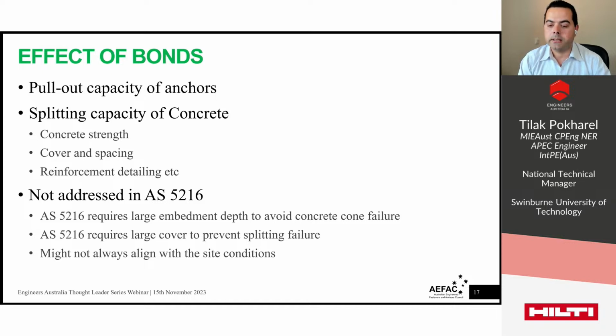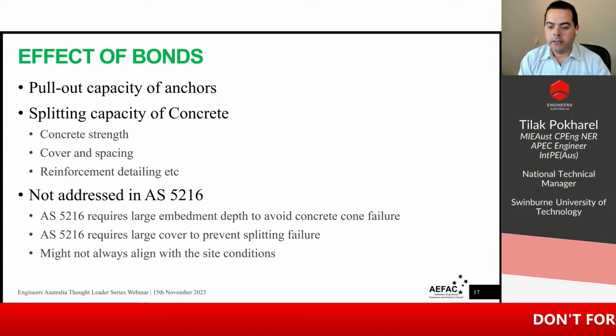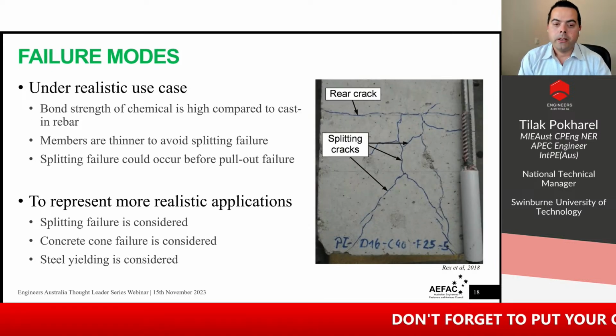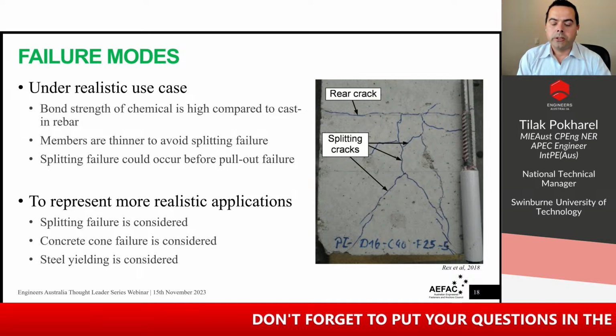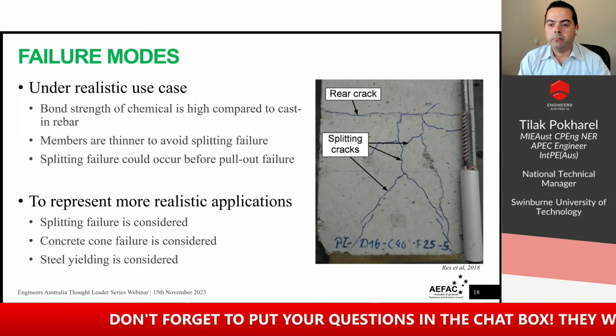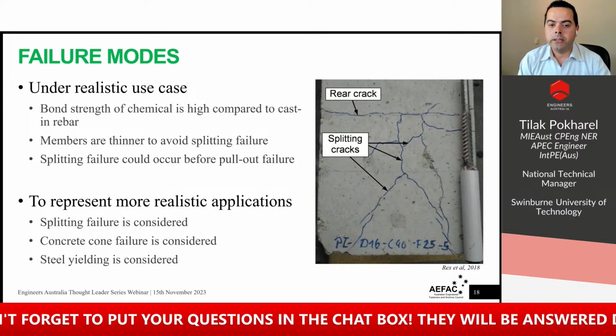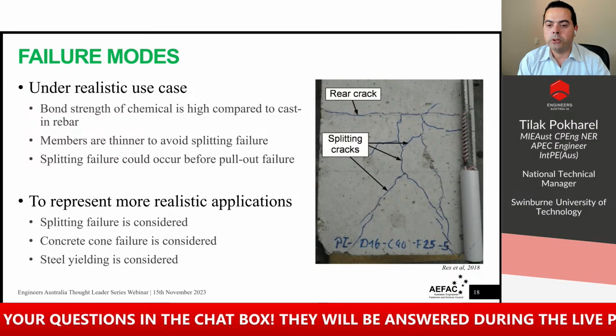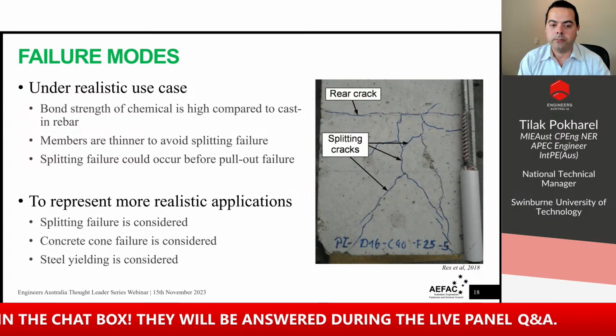For example, in the case of extension of a thin slab or connection to a small beam or small column. In real conditions, the rebar is often provided with small cover and the bonded segment is subjected to tension force in an unconfined manner. That means there is a possibility of concrete splitting and pull-out. Since the actual bond strength of post-installed reinforcing bar could be rather high, under realistic boundary conditions, concrete splitting would often govern the failure prior to pull-out of the rebar.